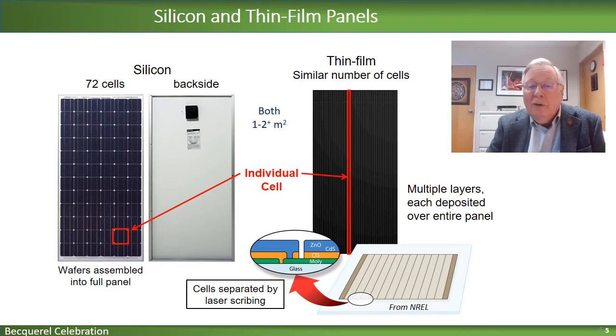And next we come to the top layer there, which is semi-transparent zinc oxide, and after it's put down, a third cut is made. So the net result is that the bottom of one cell is electrically connected to the top of the adjacent cell. And therefore, once again, they're all in series, in this case without having to hook them up individually, but just making these judicious laser scribes as the processing goes along.